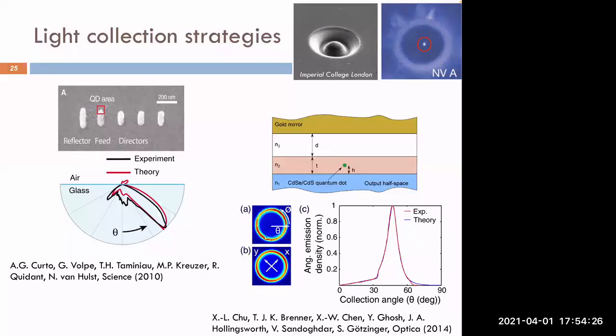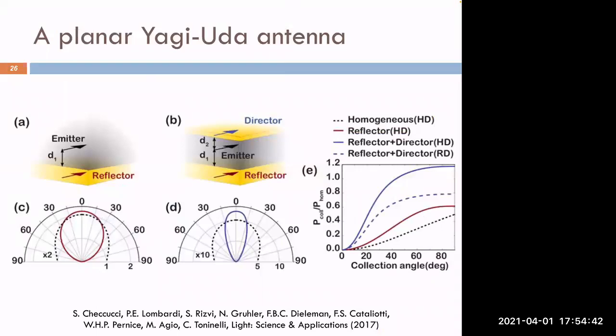And another possibility is this planar structure that gets also a very high extraction efficiency, but unfortunately at high collection angles. So these are kind of problems that are still not completely solved, and therefore we went also for this and proposed this kind of structure in which you essentially have a planar Yagi-Uda antenna. So you have thin films made of metal that essentially work as a reflector and director to be able to create passive dipoles that are coupled to the active dipole, which is our quantum emitter. And due to the coherent coupling of these elements, you can strongly redistribute the radiation pattern.